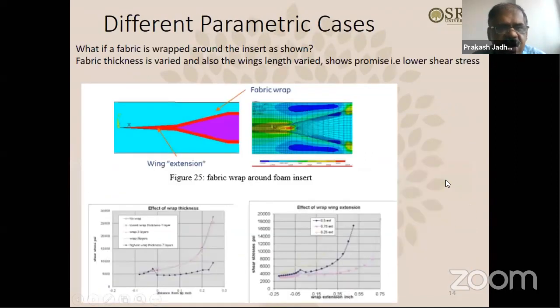So also, suppose you take a fabric, bidirectional fabric, basically woven fabric. You take a woven fabric and wrap around the foam insert and use it, okay? And also you can have kind of a wing extension, that fabric wrapping. Can we have some kind of wing extension at the end? Okay. And how much should be the length of this wing extension? Is it like 1 millimeter, 2 millimeter, 5 millimeter, how much can you have?